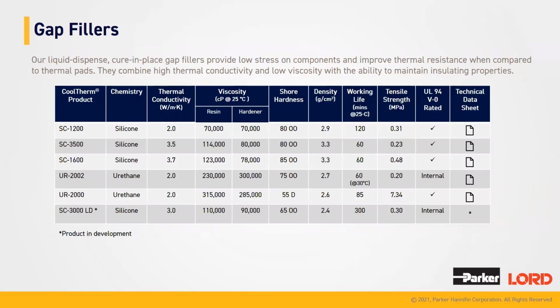Let's continue on. So going a little bit more into the details about our gap filler offering, here again you have multiple chemistries. Basically here, silicone and urethanes. You see that you have thermal conductivity available going from 2 watts up to 3.7. And one remarkable thing maybe is for the SC3000LD, where you still have a thermal conductivity around 3 watts, while the density is only 2.4, which is quite remarkable for a gap filler with this level of thermal conductivity. As you can see, there are some of the products which are also UL94V0 rated, meaning that they have a pretty good resistance to flame. I think that UL94V0 is known by most of the audience.